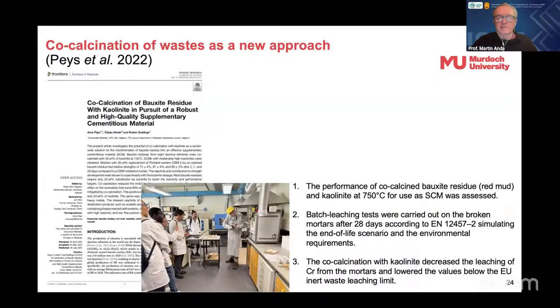And the great thing is that the challenge of using industrial waste materials in public infrastructure is that you do run the risk of leaching heavy metals and other substances, contaminants, pollutants into the environment. So we have to do leaching tests under particular well-defined standards to determine the extent of this risk. And what this co-calcination method has shown is that it decreases the leaching of particular heavy metals like chromium from the geopolymer mortars, and we were able to keep the concrete within the inert waste leaching limits as a result.